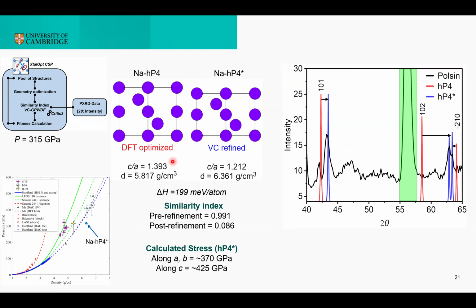The structure that appeared to give the best similarity index was a sodium HP4 which seems to be extra-squeezed along the c axis, as if the compression was not completely isotropic. This caused the c/a ratio to lower and also the density to increase. However, this structure generated with a powder X-ray diffraction match gives a diffraction that is really spot on with the experimental one, including this peak here that I didn't even notice at first glance.